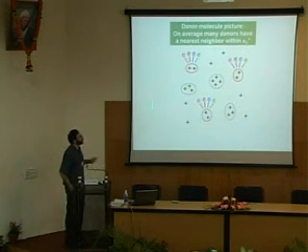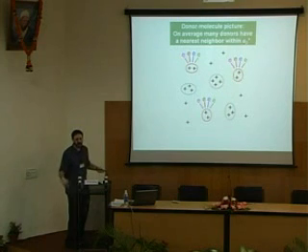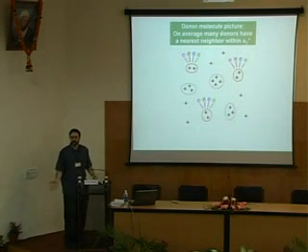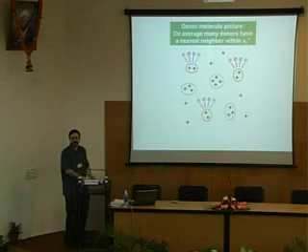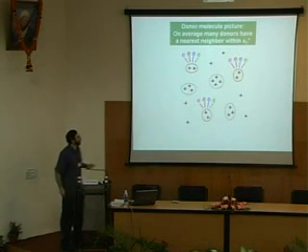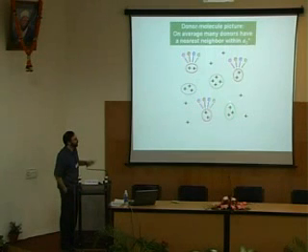In this random network of donors, maybe on average there are 15 or so that happen to be coupled with one nearest neighbor, and they all act about the same way. Therefore, that's how we could explain these broad peaks, the first peak being the first electron going on these molecules. Of course, there could be other clusters with greater numbers of dopants closer together, but these are less likely to behave in the same way.